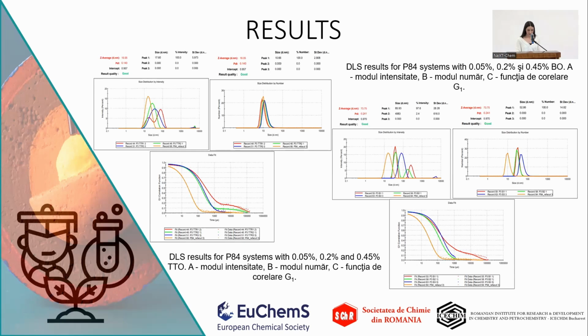For the P84 system with the tea tree oil, there isn't much of a difference. The higher the concentration, the size remained the same. But in the case of the bergamot oil, it actually had an influence on the size of the micelles, and we could say that we encapsulated successfully the essential oil.